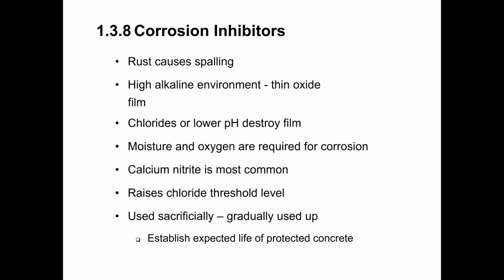Okay, so depending on how long the structure is going to be in use and the exposure conditions for that structure, that will dictate how much corrosion inhibitor should be used. Because the corrosion inhibitor is sacrificial, the effectiveness of the corrosion inhibitor does decrease over time. Gradually, it will be used up.